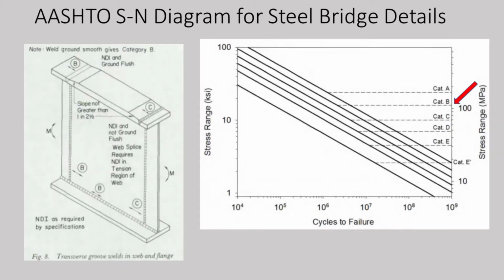Well, let's look at the overall issue of any structural detail coming into play here in that area. Transition weld is category B, flange-to-web fillet weld, category E. The run out, the endurance limit at over 2 million cycles is 16 KSI per cycle. Not likely to be caused by a weld detail. So we thought, well, it's a flaw.